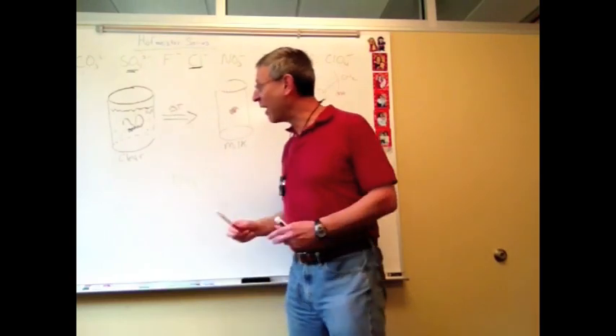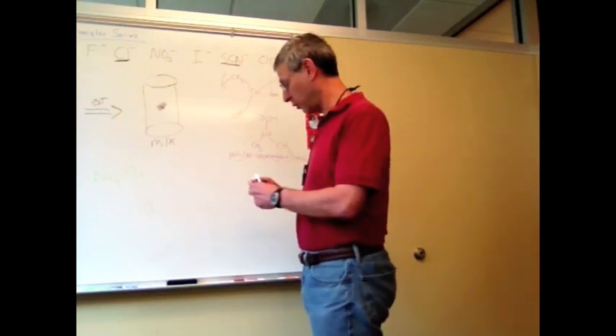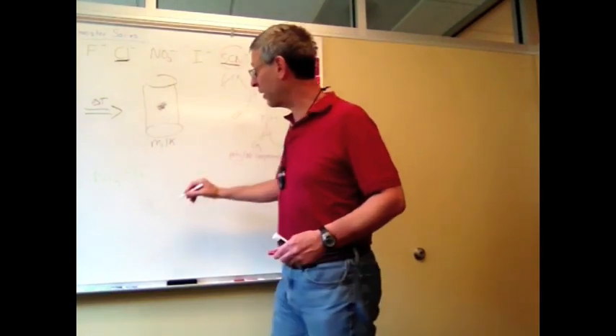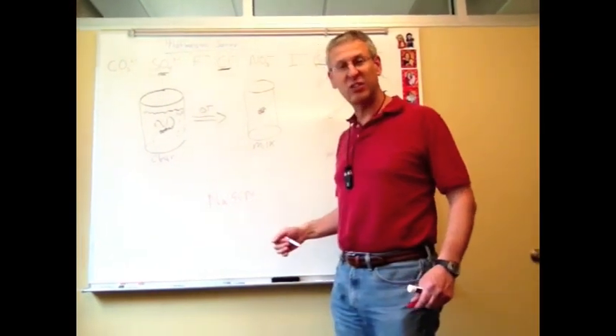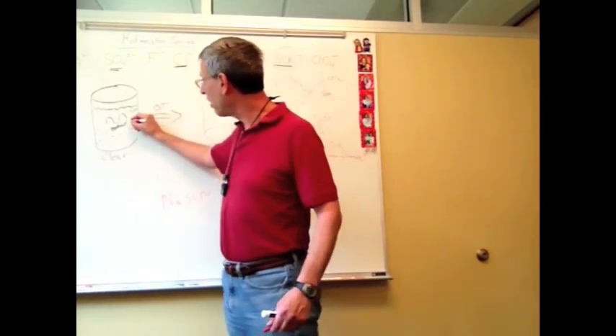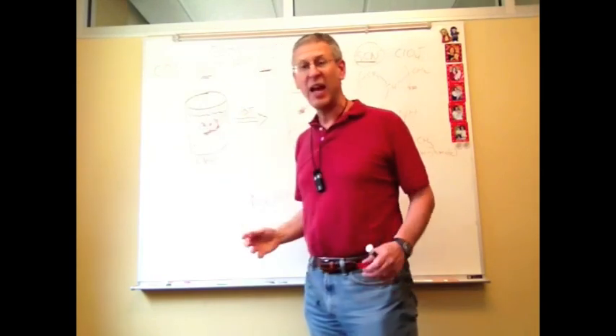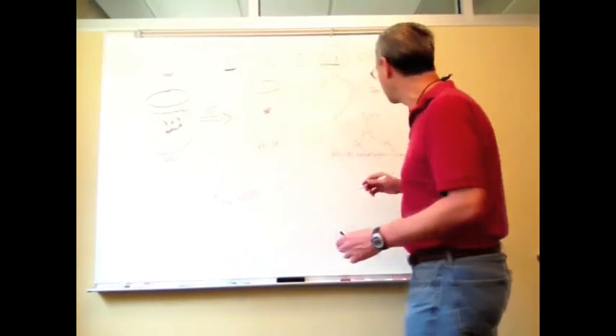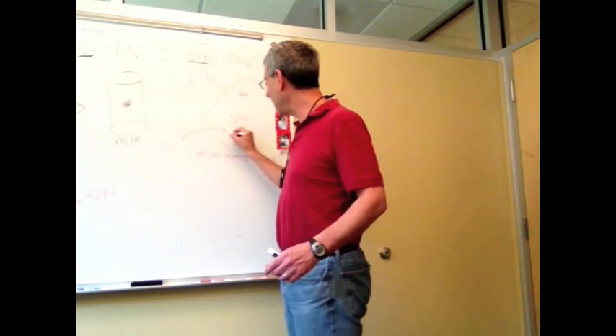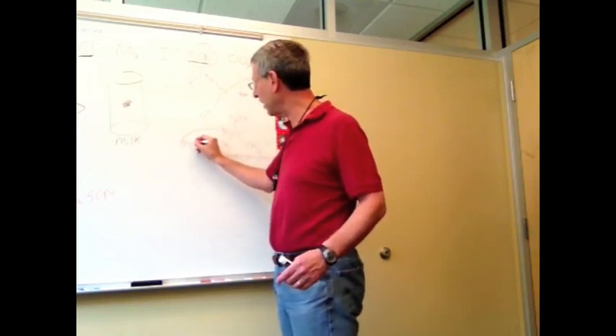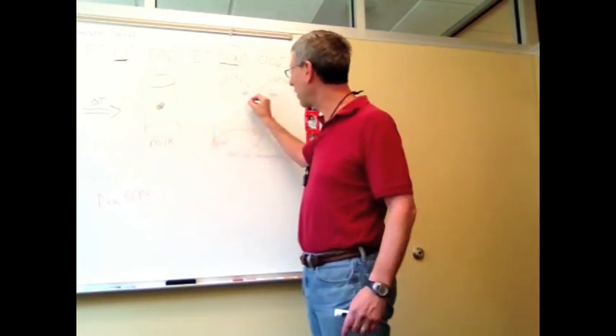On the other hand, if I pick something like thiocyanate on the other end of this series, those molecules—sodium thiocyanate—behave very differently in solution. This is a much less hydrated anion. Thiocyanate will come right up and bind to the polymer chain. If I show you this in the context of this structure, we know from years of study what the binding sites are. Thiocyanate will bind right next to this nitrogen here, at this carbon, and also over here.